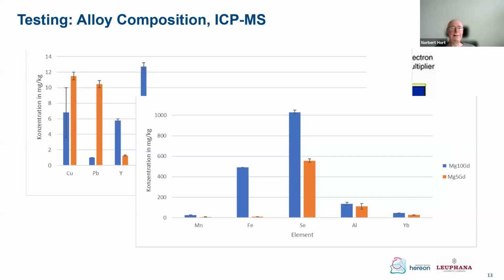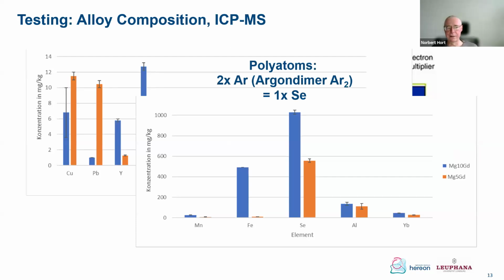That's a well-known artifact, because due to the plasma that you use to make the analysis, 2 argon atoms team up, forming argon dimer. That's not stable, but that's having exactly the same mass like the selenium. So be really careful when you get a result and you do not know about the black box that you have been dealing with before. So be skeptic.